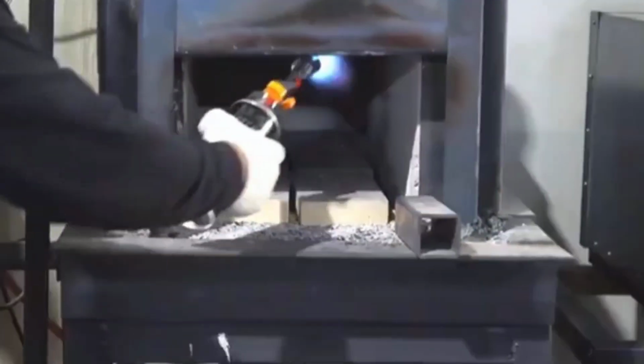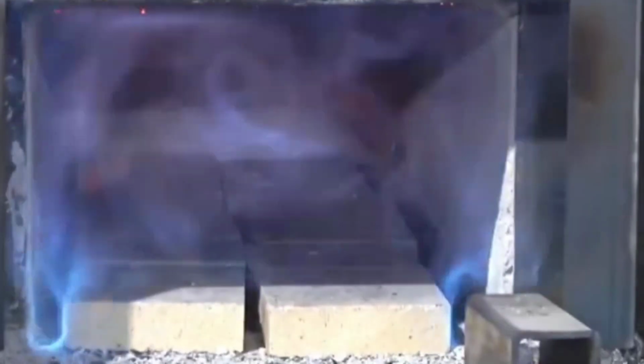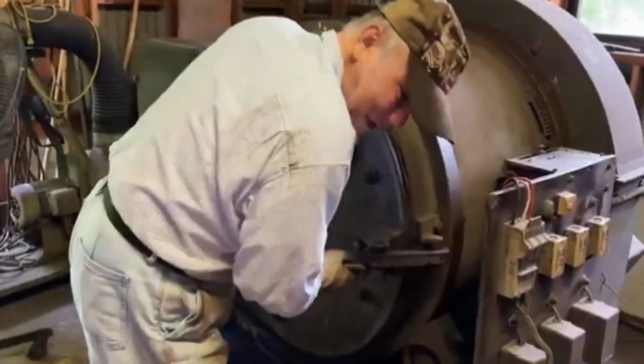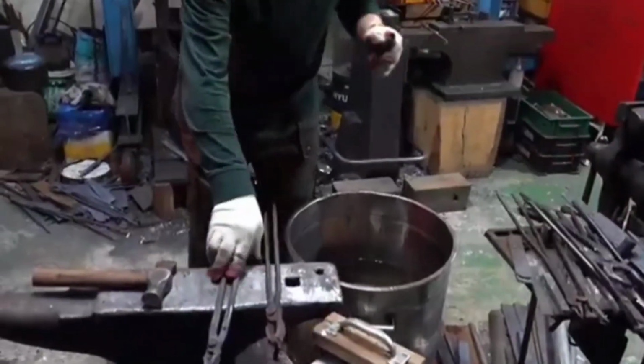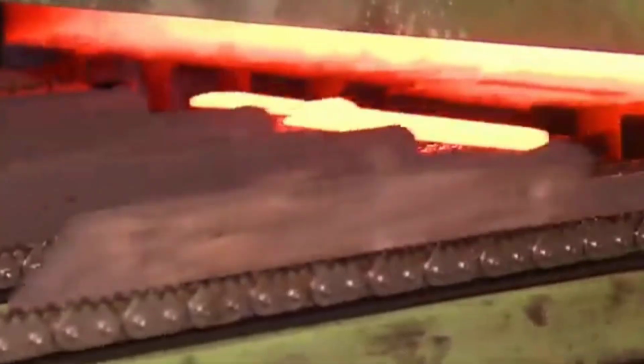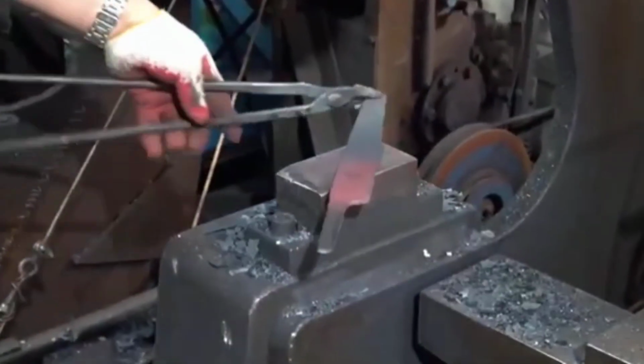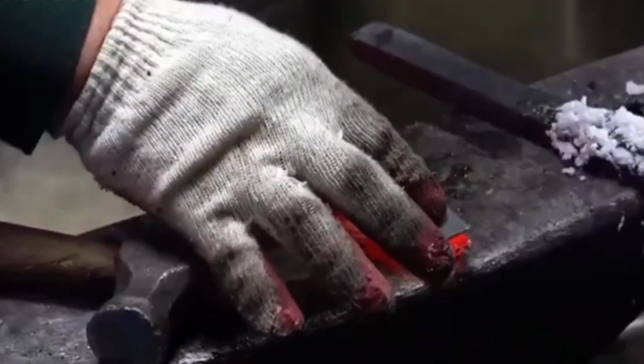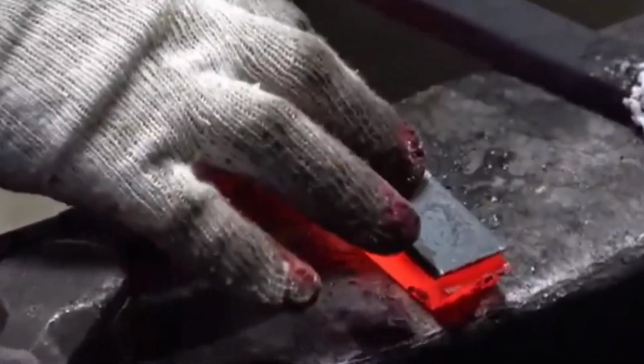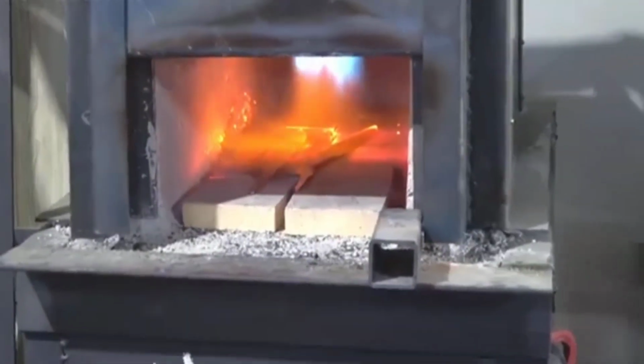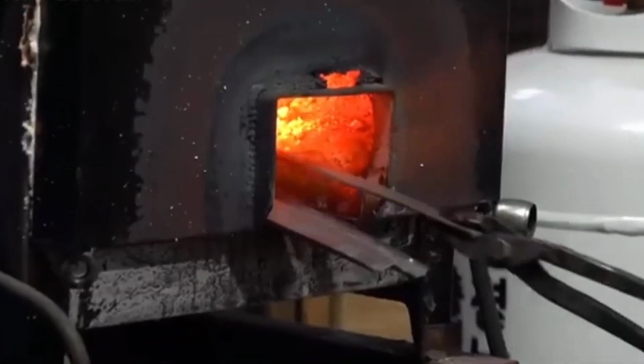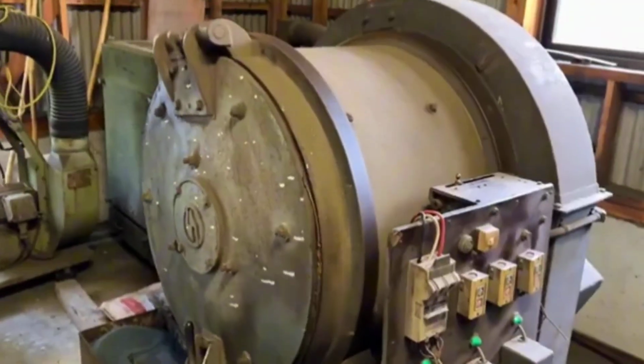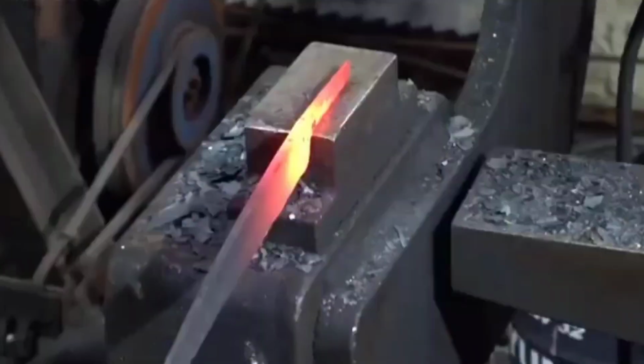After hardening, the blade reaches impressive levels of hardness, but with a hidden weakness, brittleness. At this stage, the steel is highly vulnerable to chipping or cracking under sudden impact. To counter this, the next step is tempering, a vital heat treatment designed to restore toughness and stabilize the steel's internal structure. During tempering, the blade is placed back into a furnace and held at a lower temperature, typically between 150 and 250 degrees Celsius, for 1 to 2 hours.